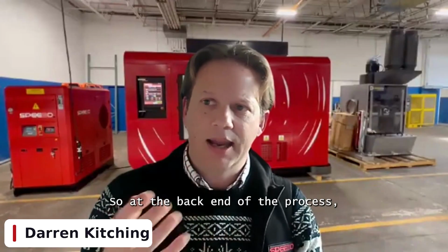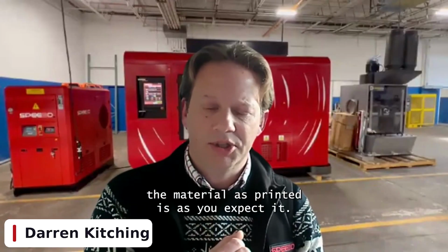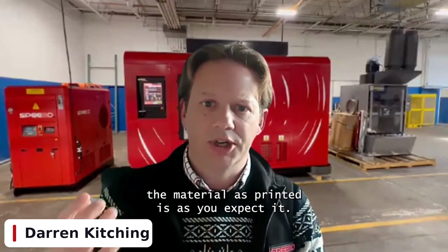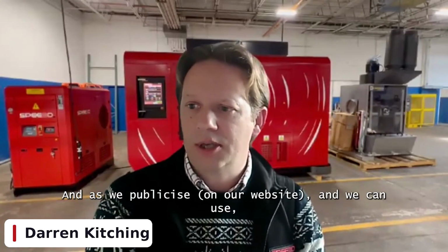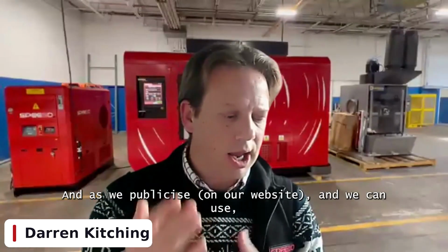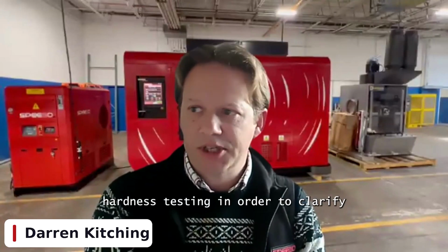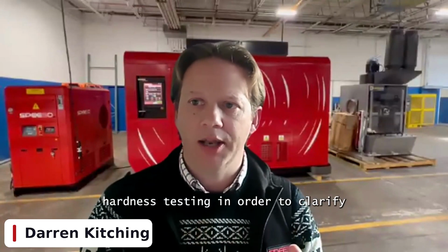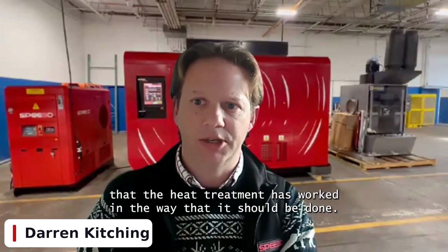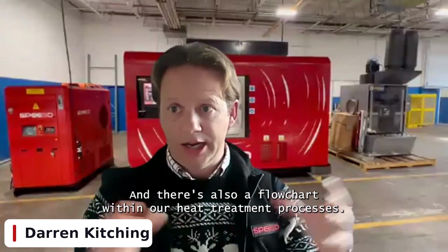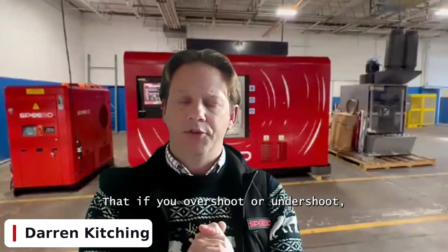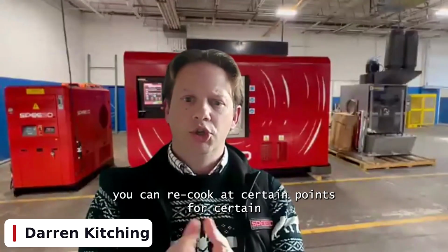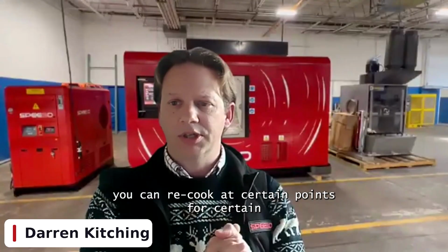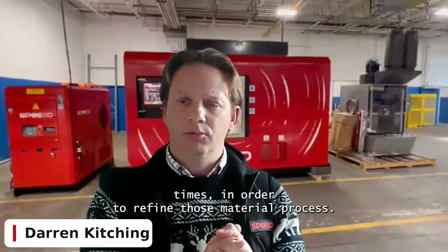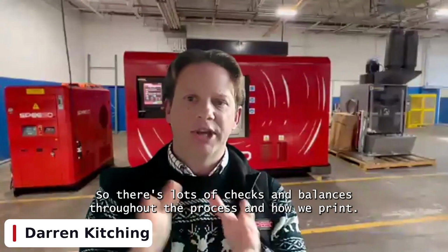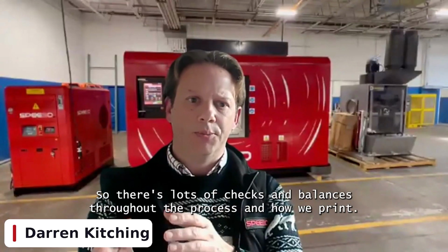So at the back end of the process, the material that's printed is as you expect it and as we publicize. And we can use hardness testing in order to clarify that the heat treatment has worked in the way that it should be done. There's also a flowchart within our heat treatment processes that if you overshoot or undershoot, you can recook at certain points for certain times in order to refine those material properties. So there's lots of checks and balances throughout the process in how we print.